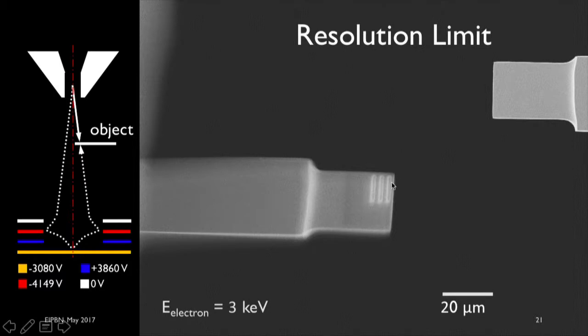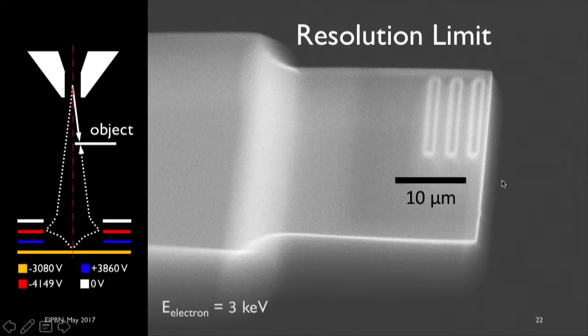So you see those lines in the reflected image, and if I magnify it a little bit more, you can see better what kind of resolutions we're dealing with. So resolution is quite a bit below 1 micron, more likely about 600 to 700 nanometer resolution. But the other observation you can make here is that only in a small region of this field of view is the image fairly sharp. Anywhere else, you see these blurry edges and some stigmation, and overall not a good resolution.